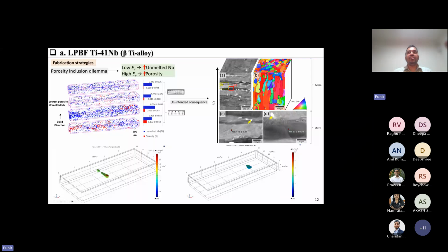Although there was one unintended consequence. If you look at these layers of the material we were able to process, in the top part of one layer you have melted all the niobium, but in the bottom section of the same layer you can see some unmelted niobium particles, and you can see this across the layers. Because of this, in one region you have a solid solution with a very high amount of niobium, and in another region the solid solution has less niobium. So there is a compositional variation from layer to layer because of the processing technique that we used.